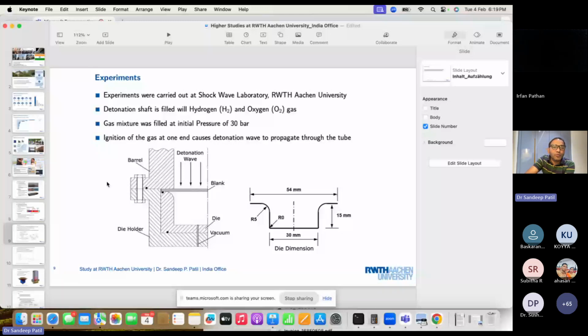Therefore, we filled the gases H2 and O2 with an initial pressure of 30 bar, and we ignited the gases at one end in order to create these detonation waves. If you look here, even though there's one die, there's also a die holder, because it's creating huge pressure. It is from 30 bar to almost 150 bar. So it's a huge amount of pressure getting created in this method.